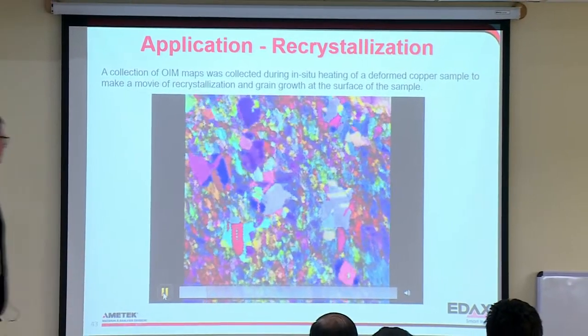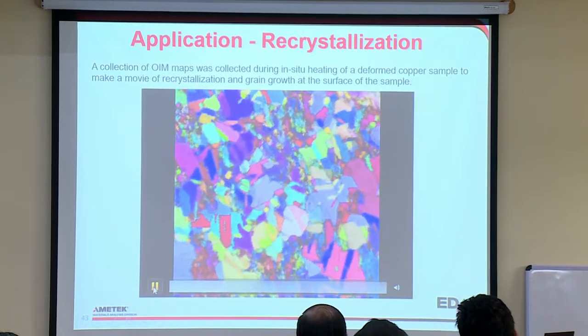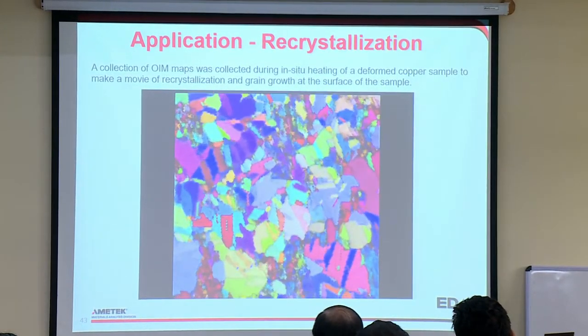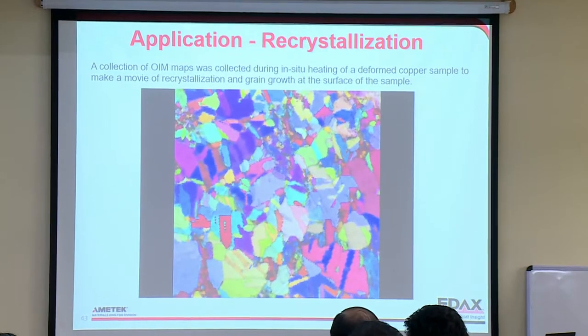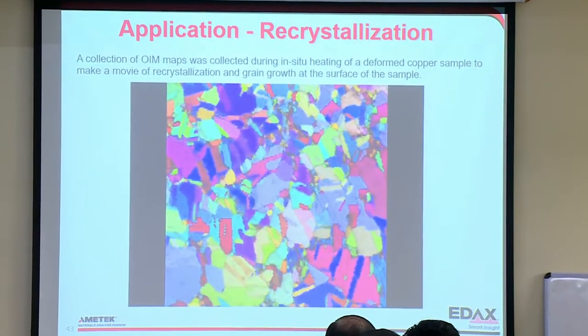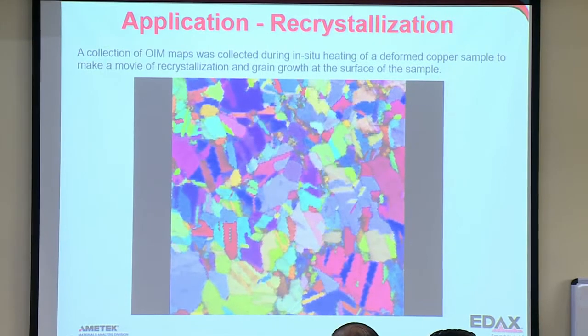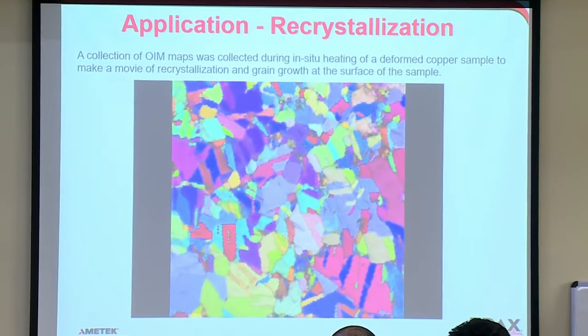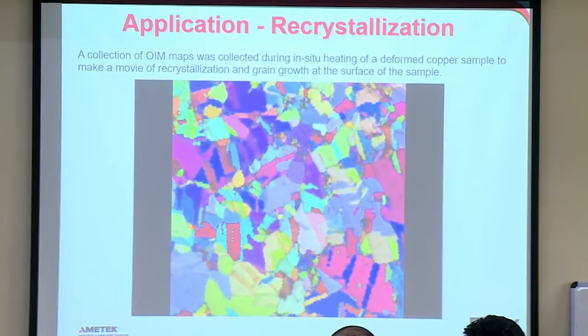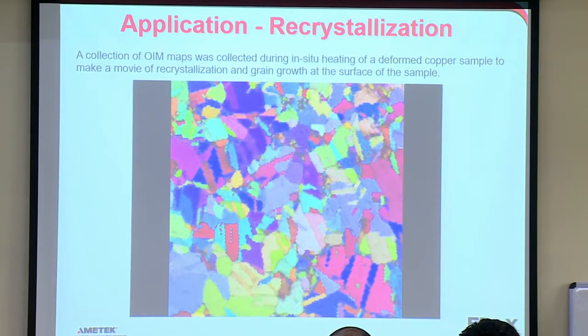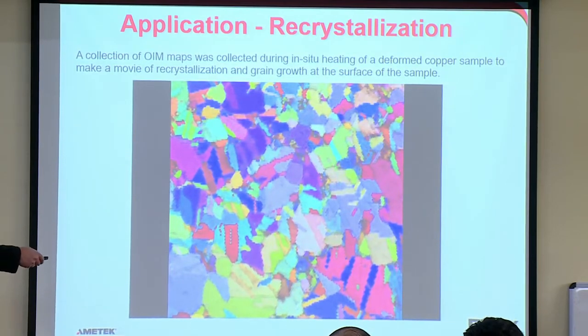So you can see recrystallization starting to happen. You get these grains popping in that are all solid color, and the twins that are forming. It's jumping around a little bit because we couldn't quite get a line between each slide. But you can really see the deformation happening. And you can see there are some areas that did not recrystallize. Let's see some of these small areas here.